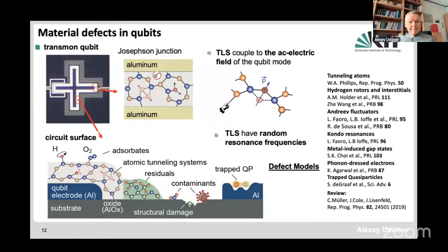Now, it turns out that these devices, already when they appeared, even before the transmons were invented, in the phase qubits at that time, people found that the energy spectrum of the device is non-continuous. There are some frequencies which show avoided level crossings with some defects. And these avoided level crossings can be of different scales. It could be really comparable to, let's say, detectable frequencies, in the range of a few megahertz, but could be simply some frequency where the coherence is decreased.